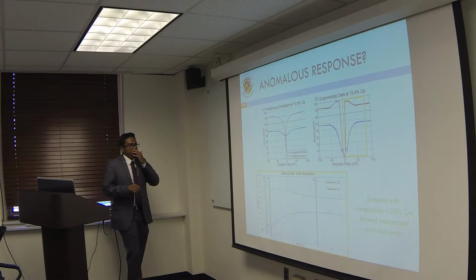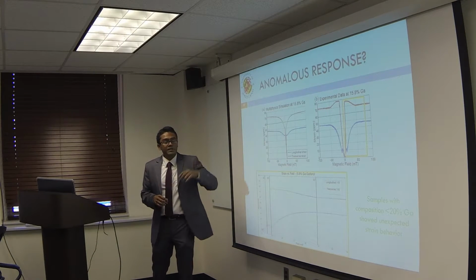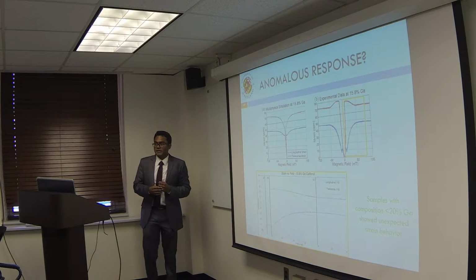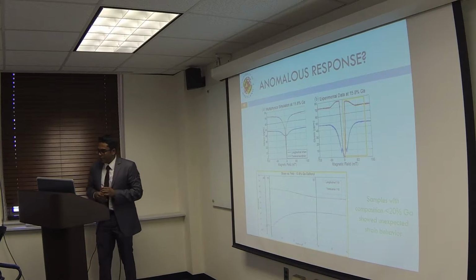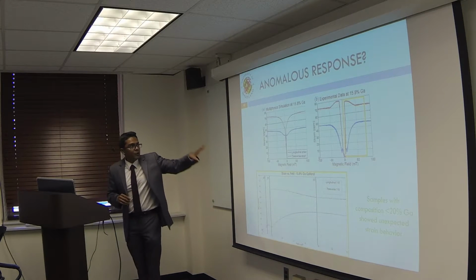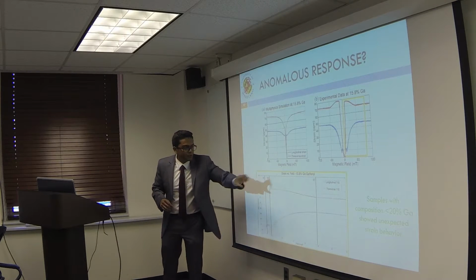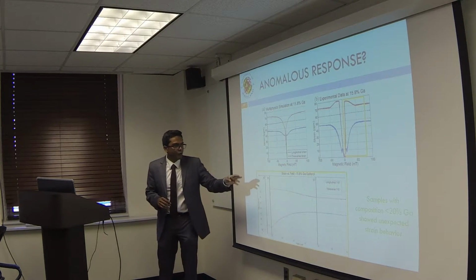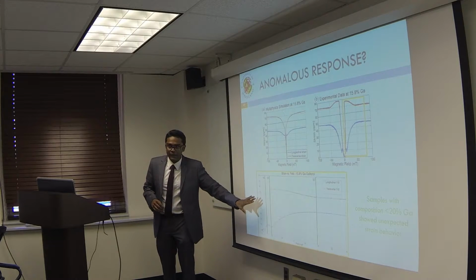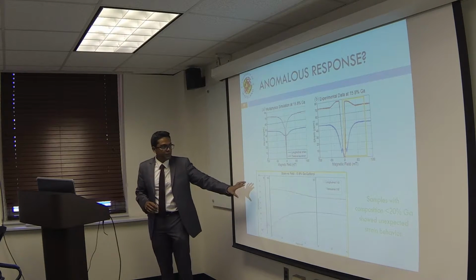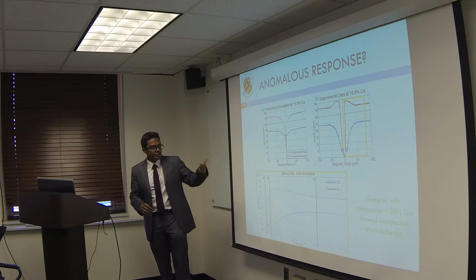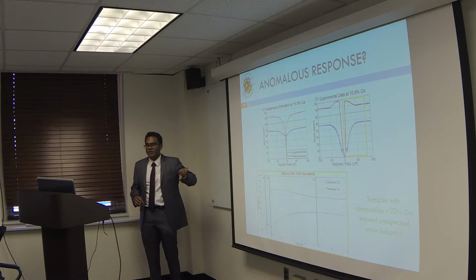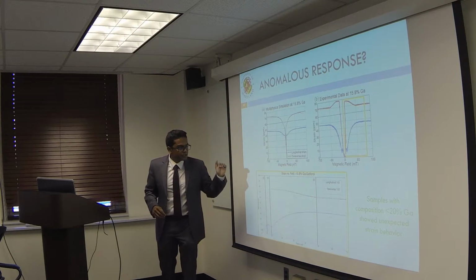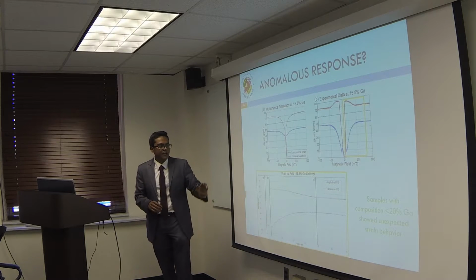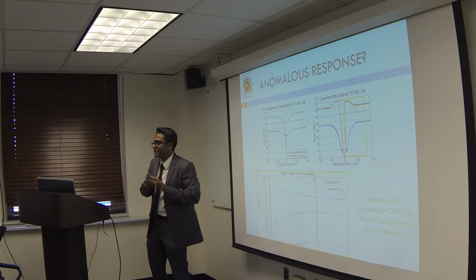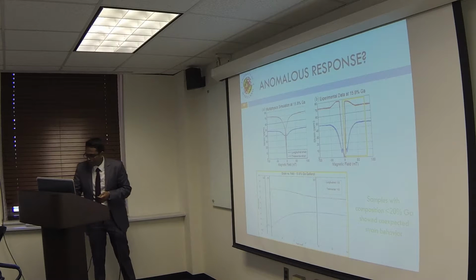Now to the interesting part. We still haven't discussed why we see a non-monotonic increase in the longitudinal and the transverse strains. To understand what's going on, we decided to split up the strain curve into 4 distinct regions. We have region A, where there is an increase in both the longitudinal and the transverse strains. We have region B, where there's a sharp increase in the transverse strain, but a decrease in the longitudinal strain. Past B, there's a decrease in the transverse strain and an increase in the longitudinal strain. And past D, we achieved magnetic saturation.